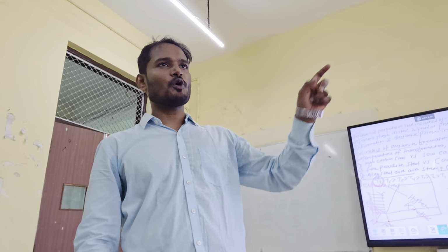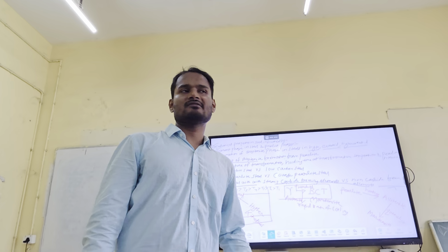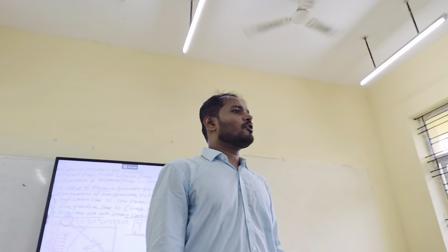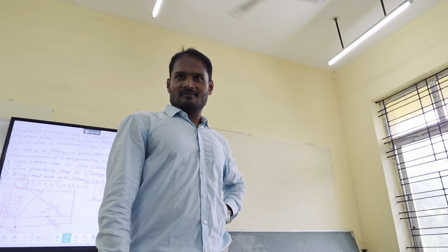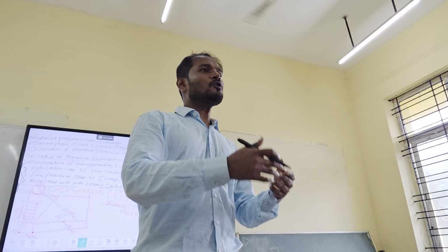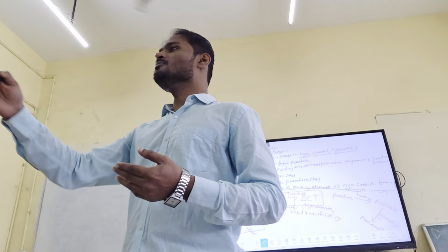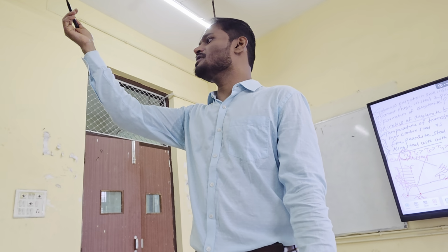So the second point is that the holding time also affects the kinetics. Higher the holding time, higher the kinetics, you can say. Or in other words, more nucleation and more growth will happen if the holding time is more. Obviously, because this transformation happens due to nucleation and growth. So more holding time means more nucleation, more growth. Similarly, higher the transformation temperature, higher the nucleation and higher the growth.